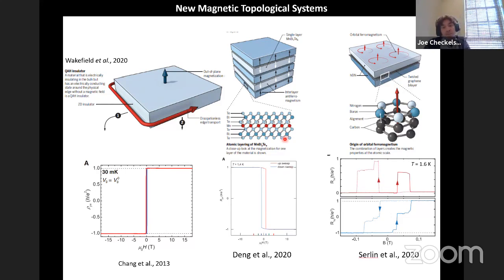And very much that was what was realized very recently, that if you could isolate, using these exfoliation techniques, just one of these, this is 7 of the layers, but if you stack an odd number of them together, you could realize something that looks a lot like this original quantum anomalous Hall effect, but in this intrinsic material. And indeed, compared to this original experiment done at 30 millikelvin, this is at something like 1, 2, 3, 4, 5 Kelvin, where you can see this kind of quantization.